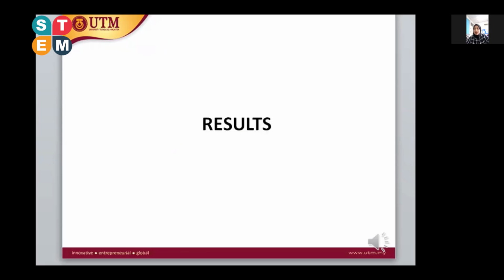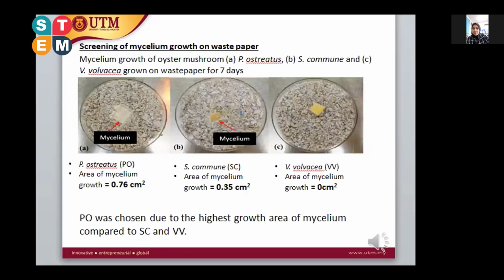So next, here are the results. Preliminary screening of mycelium was conducted at room temperature for 7 days. The mycelium growth of PO, P. ostreatus, and S. commune on waste paper was determined with areas of 0.76 cm square and 0.35 cm square respectively, while no mycelium growth was detected when using V. volvacea. Hence, PO was selected as the most suitable fungus to grow on waste paper compared to the other fungi.